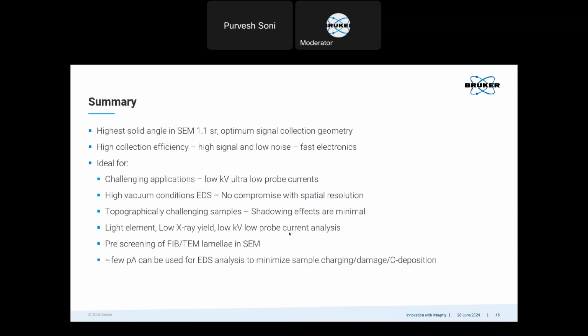So with this, I reach the end of this webinar. To summarize, I would say that the flat quad has the highest solid angle for SEM EDS. It's 1.1 steradian because of the sample-detector geometry. It sits right above the sample, and this is why the solid angle is so high. And if you combine this with the high takeoff angle and the fast electronics that we have, then you can get a very high signal to noise ratio for EDS measurements.